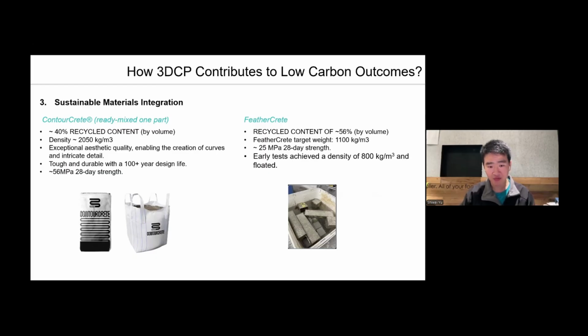We have also been developing a lightweight mix called Feathercrete, which contains even higher recycled content. Its target density is around 1,100 kilograms per cubic meter, and strength in 28 days is around 25 megapascals. But in the earliest testing we did in the factory, we could even achieve a lower density, around 800 in our test. To support different project needs, we supply ContourCrete in different bags, like 25 kilogram bags for small applications and 1 ton bulk bags for large-scale construction jobs.